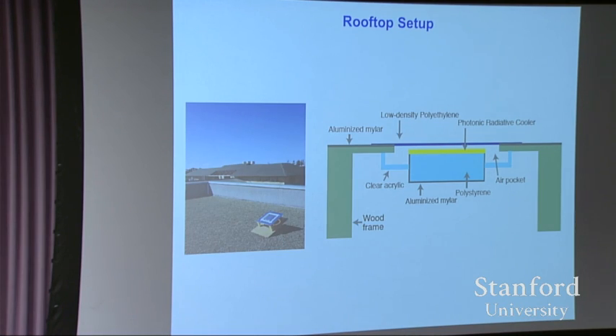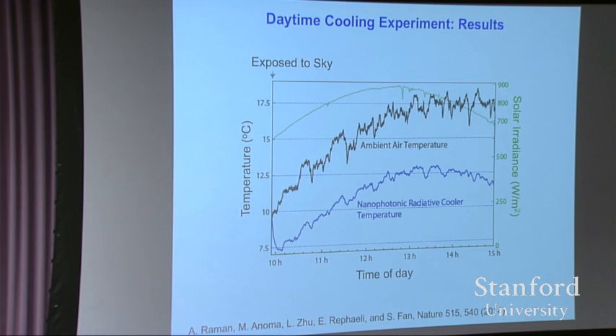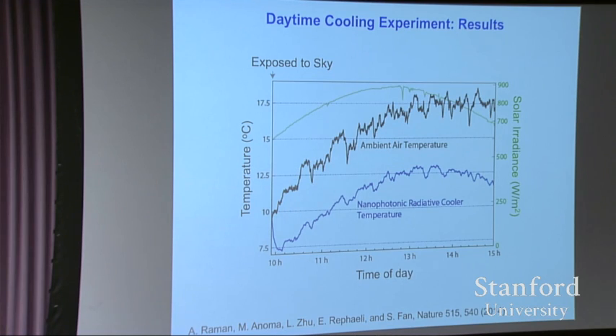Yeah, so the temperature of the ambient is measured under the shade, but outside the box. And the temperature of the sample itself is measured by thermocouple at the backside of the sample. If you look at the data itself, what you do see is substantial temperature fluctuation both in the ambient air temperature and the radiative cooler temperature. As far as non-equilibrium effect is concerned, in this case, the thermal insulation is still not perfect yet. So in fact, the response of this is very fast because there's still a substantial heat leakage from this into the ambient. So you may probably infer some time constant measure from here.